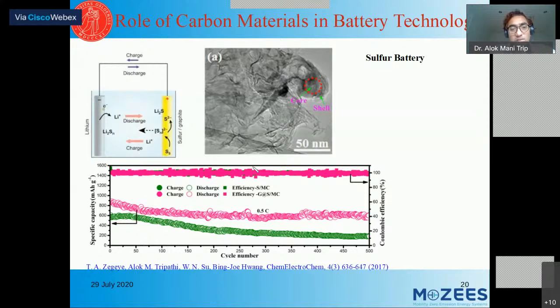If we talk about energy density, a lithium-ion battery can go to a maximum of around 200 to 250 watt hour per kg. But the sulfur battery is still in a developmental stage, and some companies are commercializing it also. This can give you 400 watt hour, almost double the capacity of the lithium-ion battery. This also has lithium, but it is called the lithium sulfur battery, or commonly the sulfur battery.